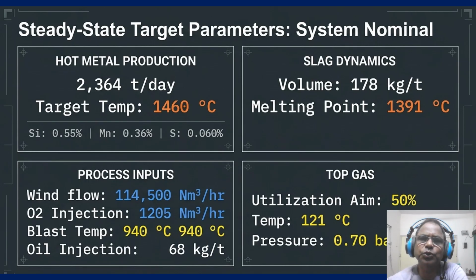Our process input shown in the bottom left include a wind flow of 114,000 normal meter cube per hour and an injectant rate of around 60 to 70 kilogram per ton. So note the top gas utilization aim of 50%. So these represent a balanced state where kinetics and thermodynamics are in synchronization. So when your hot metal temperature starts drifting towards the 1391 degree, around 1400 and slightly less, you are not just losing quality, you are losing the physical ability to move liquid through the furnace. So despite this clear target, a series of missteps pushed the system across a critical threshold into a total collapse.